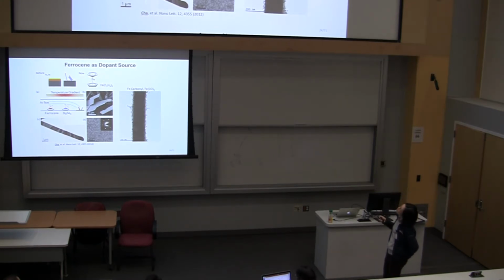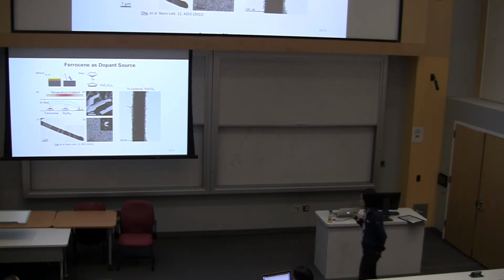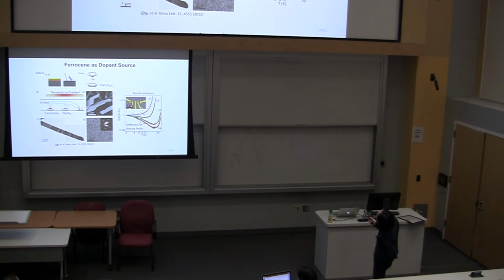So this actually worked, and we can show the Kondo effect. When I later used iron carbonyl instead, probably some iron still got doped, but the surface was also decorated with lots of iron particles. So the choice of precursors is also important in growth. This is using ferrocene, with different iron doping levels.